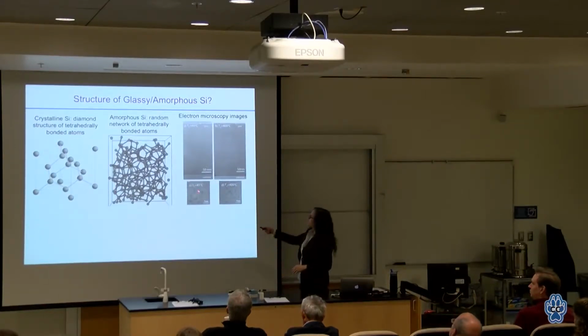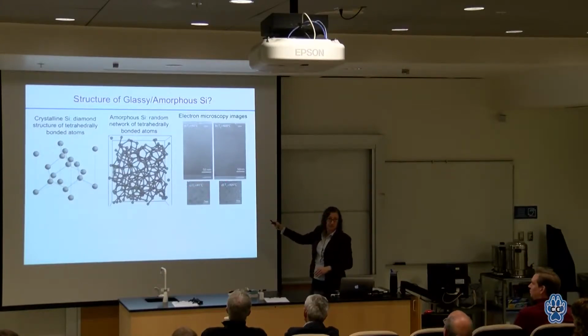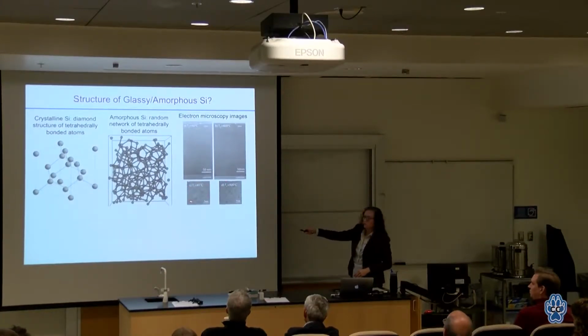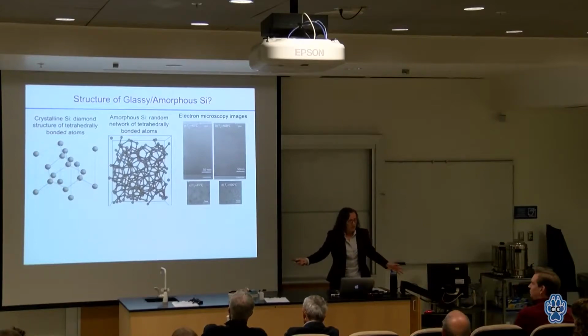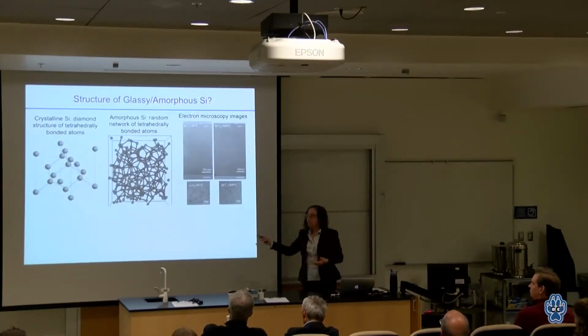And so this is a film grown at 45 centigrade, and this is a film grown at 400 centigrade. This is a high-resolution transmission electron microscope (TEM) picture, and you don't see anything. That was sort of my entire point here. There's really nothing to see.